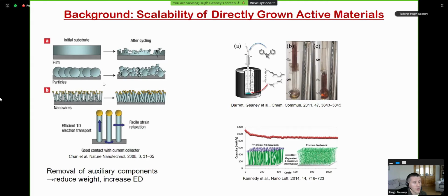Nanowires on the opposite side are a more attractive geometry, because you can have expansion radially and also along the length of the wires, and essentially you can accommodate that volumetric expansion without pulverizing and destroying the material. The directly grown materials are also attractive because you have a good contact with the current collector, so you can remove auxiliary components like the binder and conductive additive, potentially reduce the weight and increase the energy density.